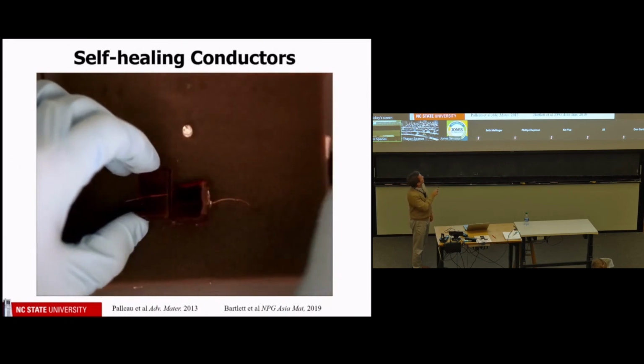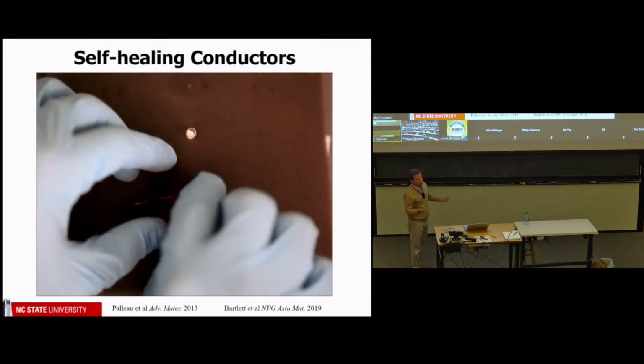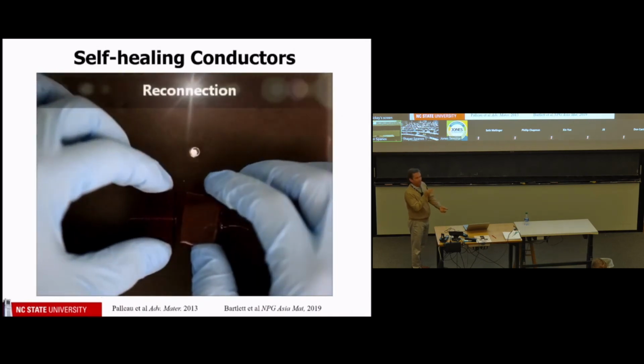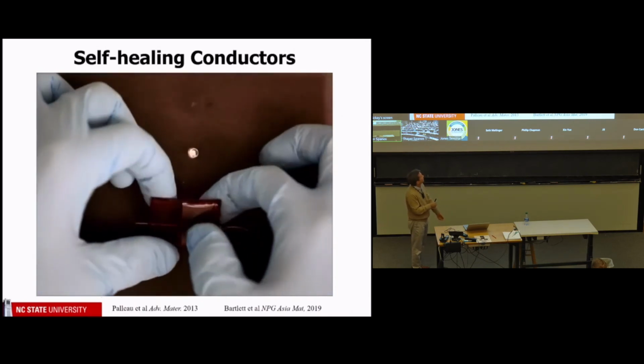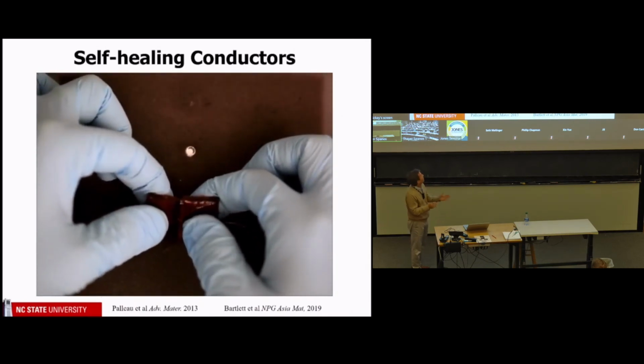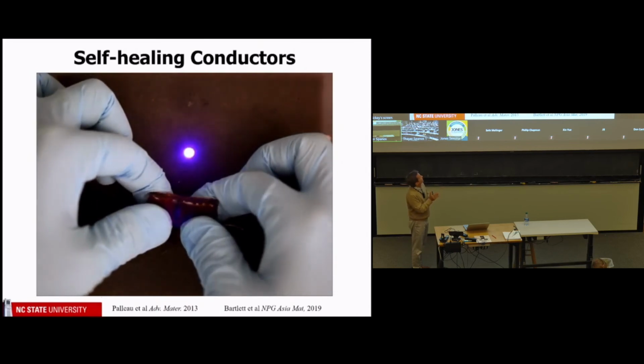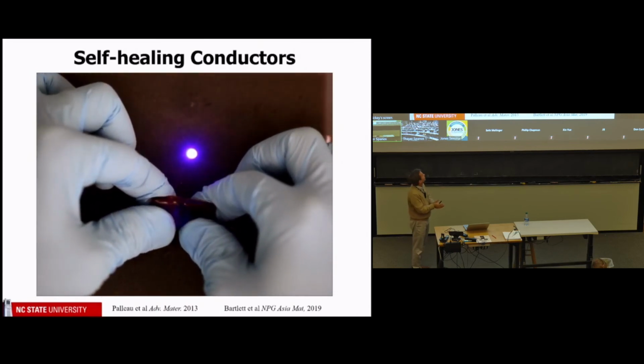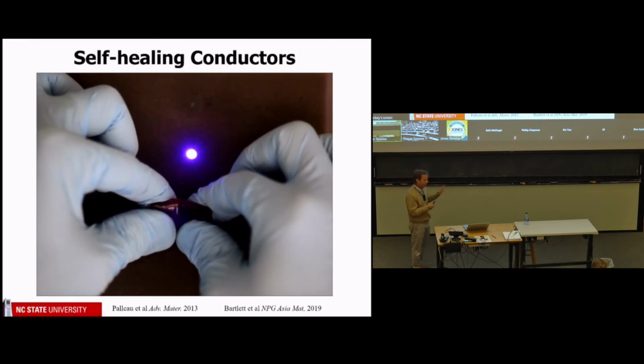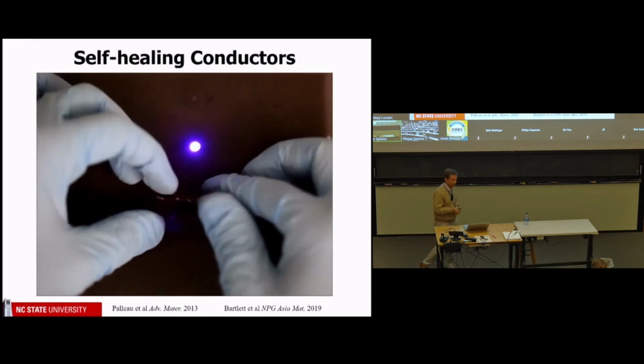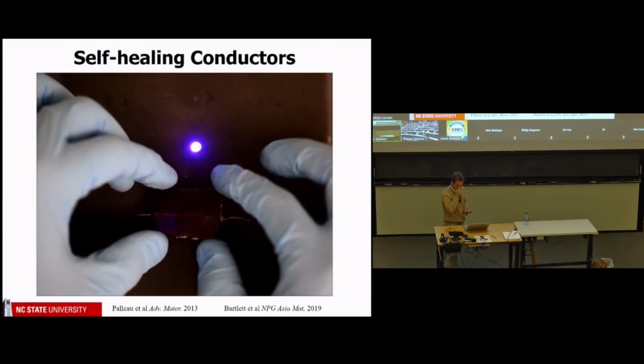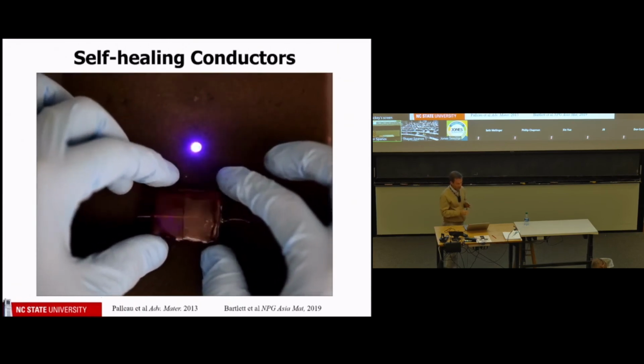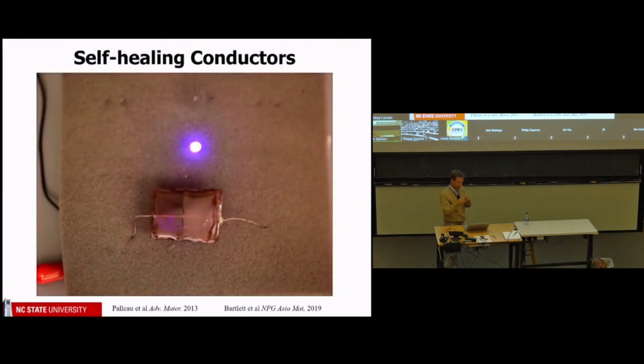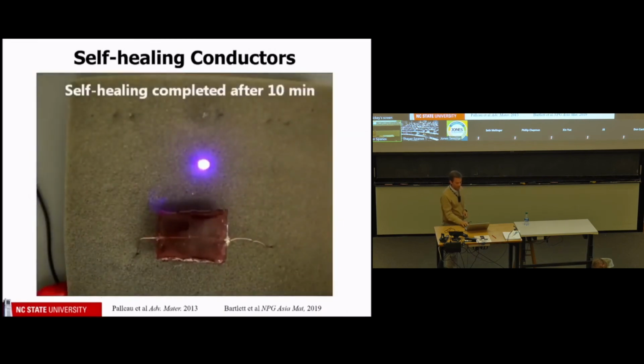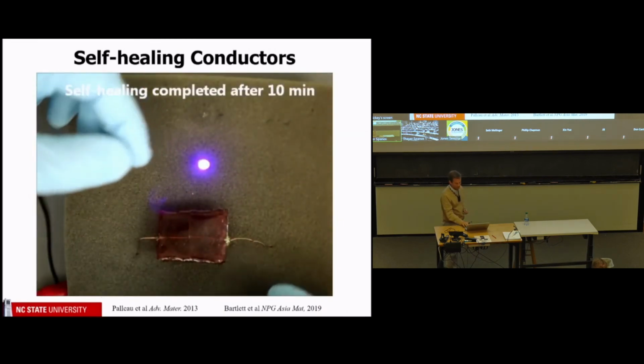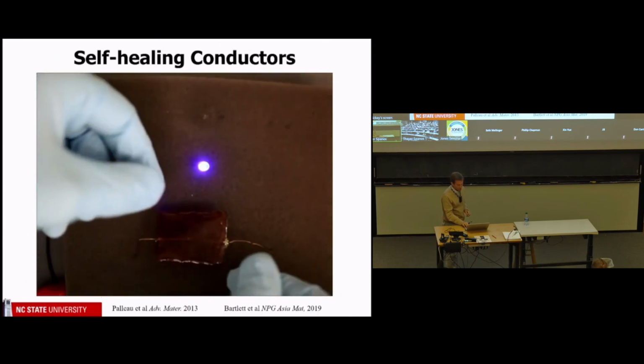And the key idea, though, if you look, it's a little hard to see, but the liquid doesn't come gushing out. It forms that oxide so fast that it stays flush, just like when you cut your skin, you form a scab. And it's flush with the interface, so when you bring it back together, it heals electrically. And then the polymer goes back together. In this case, it's using hydrogen bonding to go back together. So you have to wait about 10 minutes, but you don't need to heat it. There's no light. You just wait. Those hydrogen bonds wiggle around, find themselves, and it regains its original modulus. So you can come pull on it.